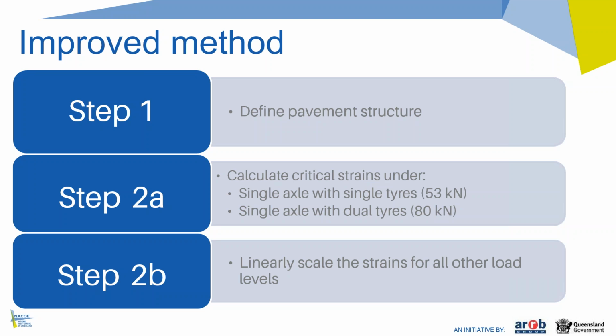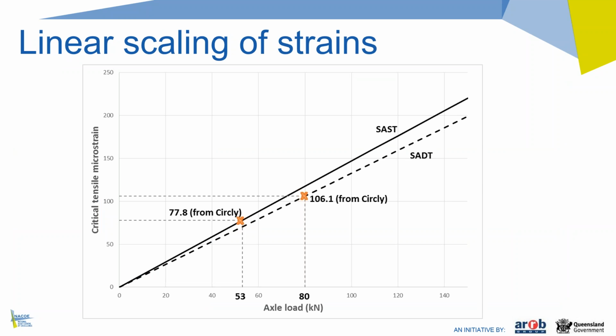Then in step 2B, the strains from step 2A are linearly scaled to give the strains at all load levels. Linear scaling is possible because the CIRCLY method is based on a linear elastic model where strains are linearly proportional to the applied load. This slide shows how the linear scaling of strains works. The chart plots the microstrain in the asphalt versus the load level. The orange crosses are the output strains from CIRCLY determined under a single axle with single tyres at 53 kilonewtons and a single axle with dual tyres at 80 kilonewtons. By drawing a straight line through these points, it's possible to determine the strain at all load levels with no need to rerun any further calculations in CIRCLY at these different load levels.